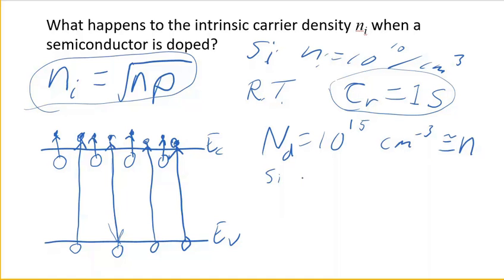In silicon, at thermal equilibrium, in intrinsic silicon, intrinsic means no dopants, you have 10 to the 10th holes per cubic centimeter, and 10 to the 10th electrons per cubic centimeter. Roll that backwards. Now you go and dope it,